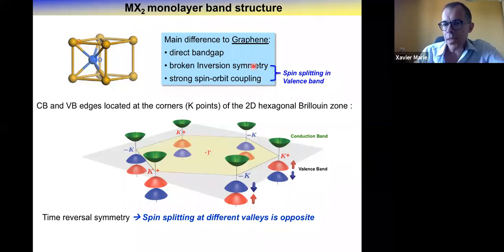And because of the interplay between this broken inversion symmetry and spin orbit coupling, you have this spin splitting in the valence band between spin up and spin down states of hundreds of millielectron volts. We'll see later that there is also smaller spin splitting in the conduction band, which will play an important role on optical properties, but a much smaller amplitude, a few tenths of millielectron volt.